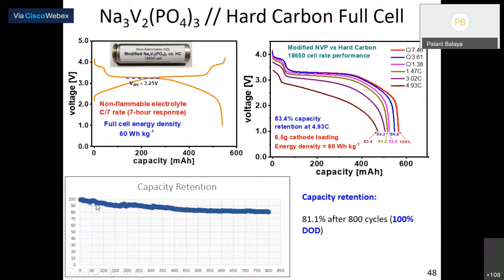And the cycle life is also shown here, retaining 81% capacity up to about 800 cycles. So please remember, if you want to commercialize anything, minimum you should achieve 500 cycles. So in this particular case, 800 cycles. We have gone up to 1,000 cycles, but then the capacity retention is about 78%. We are still working to improve the cycle life close to about 2,000 to 3,000. Ideally, 5,000 cycles is the target.